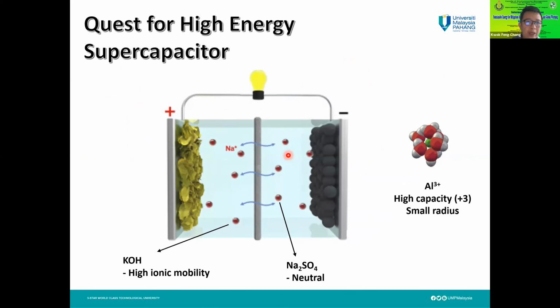For my group, actually, we are doing a quest. I told my research group that we are doing the quest for the high energy supercapacitor. I gave them a challenge. This is a common setup for the supercapacitor. Normally, the electrolyte that we use is potassium hydroxide. Why do we use potassium hydroxide? Because it has a very high ionic mobility. The other common electrolyte is sodium sulfate. Sodium sulfate has been popularly used because potassium hydroxide is highly corrosive. If you want to apply it in industry, there are a lot of safety concerns to consider. So it has been replaced by sodium sulfate. Sodium sulfate is neutral, and that is a very common electrolyte used nowadays.